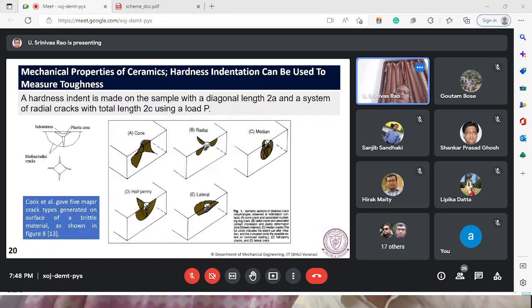Now, gradually, what we need to obtain, and the tendency, the final aim is to obtain crack free surface. For that, actually we need to check when that crack forms. The hardness indentation is the starting point. So when we have different levels of indentation, normally there is a plastic zone. When you further increase, radial cracks are there.